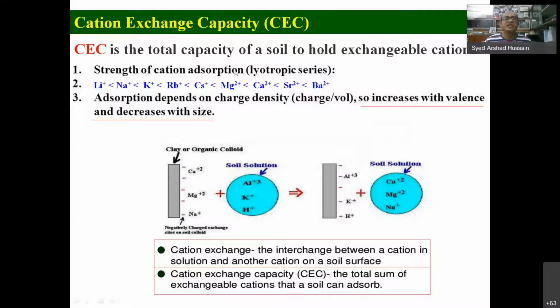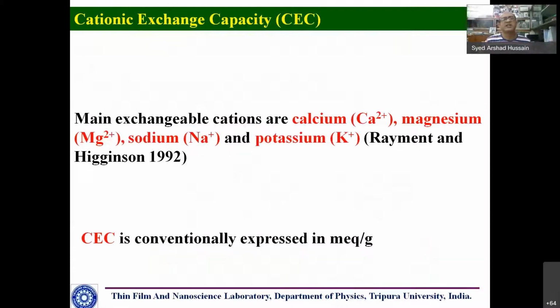Okay, and this strength depends on so many factors, but there is a series. This is called the lyotropic series. This is the order of which one has higher exchange capacity. Then also it increases with the valence and decreases with size. So in this way one can incorporate guest material within the clay systems. Okay, and CEC is conventionally expressed in milliequivalents per gram.